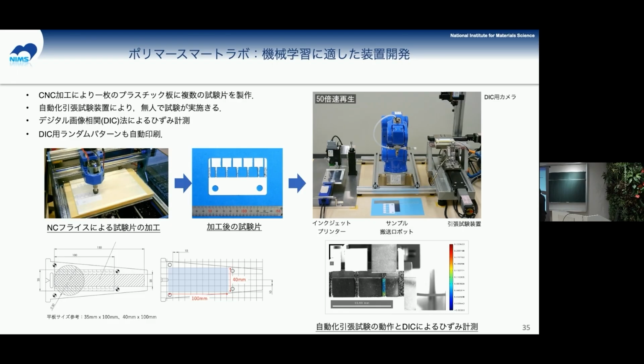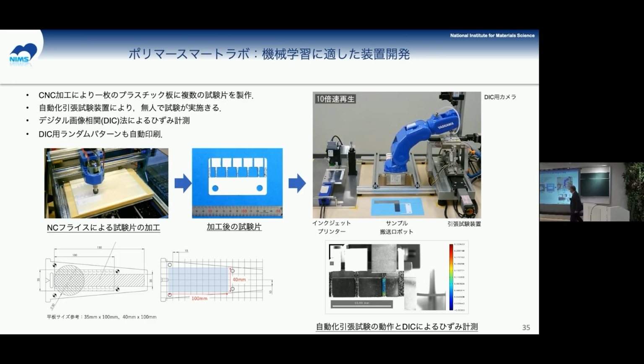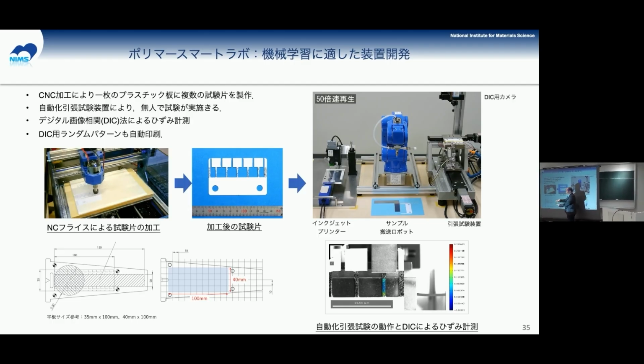This is for the mechanical properties. First we prepared credit-card-sized specimens, five specimens, and make the patterns using the printers. Then we transfer the sample to here, where we pull the samples.